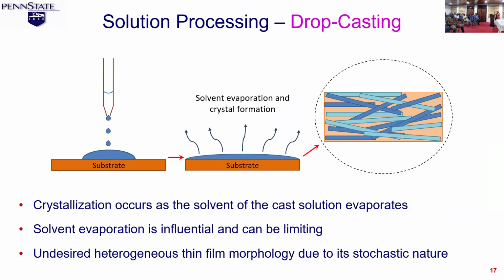So the rudimentary technique is known as drop casting, and I'll say it is the worst of all of them. What drop casting is, essentially, is taking the semiconductor material, which is TIPS-pentacene. It comes in a powdery form, and then it's dissolved in a solvent. One common solvent is known as toluene. Once you dissolve it, you get a solution that is then deposited onto a substrate. So that's what we have on the left-hand side.